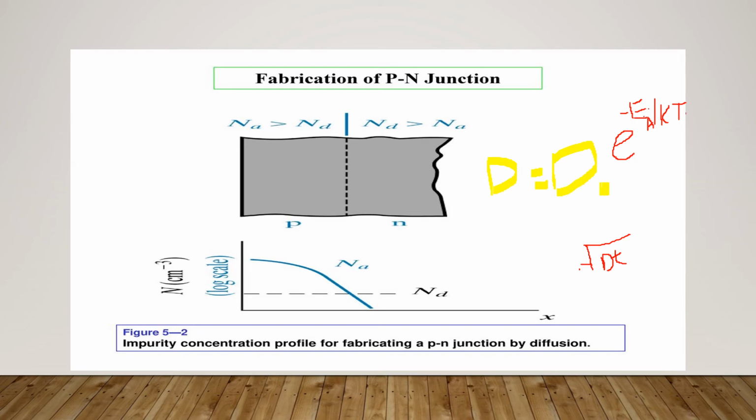If the source of dopant atoms at the surface of the sample is limited, for example, a given number of atoms deposited on the silicon surface before diffusion, a Gaussian distribution is obtained. On the other hand, if the dopant atoms are supplied continuously such that the surface concentration is maintained at a constant level, the diffusion follows what is called a complementary error function.